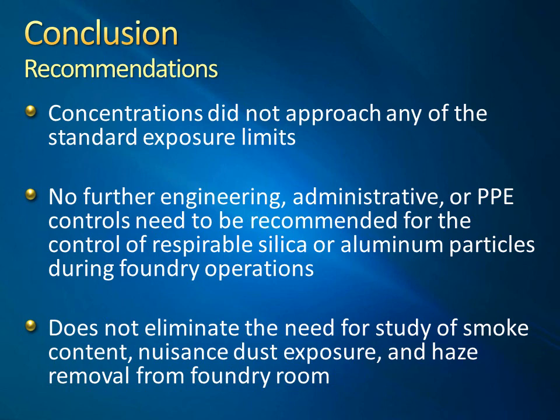The low exposure rate for these particles does not eliminate the need for area assessments and exposure measuring for other possible airborne hazards from the casting process. The pour circulation in the room should be addressed to better remove the smoke and haze after the pour. Further analysis of the chemical content of the smoke from the casting should be performed to determine if the incomplete combustion of the mineral oil found in the green sand can be controlled. The amount of respirable dust collected may infer an overexposure to nuisance dust or smoke particulates generated from the casting process. And if castings are to be prepared that require a full finishing with mechanical grinding and polishing, the amount of particulates in the air will need to be assessed.